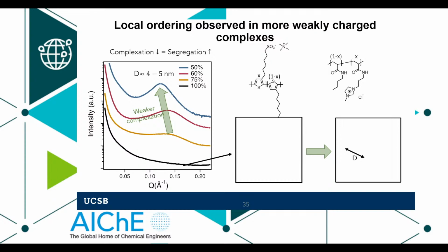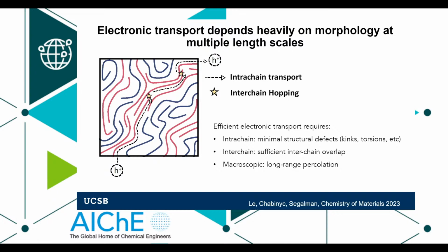Those of you who've thought about block copolymers, that's about a factor of 5 to 10 smaller than a block copolymer naturally segregates. It probably leads you to a cartoon that looks like this, where the chains are segregating into 2 different phases, red and blue. You have both intrachain transport, where the electrons are moving along the backbone, and also the ability of charges to move between backbones. It's got to be that we are improving both the intrachain and the interchain transport in order to get this kind of improvement, and then also getting long-range percolation of all of the structures, right?